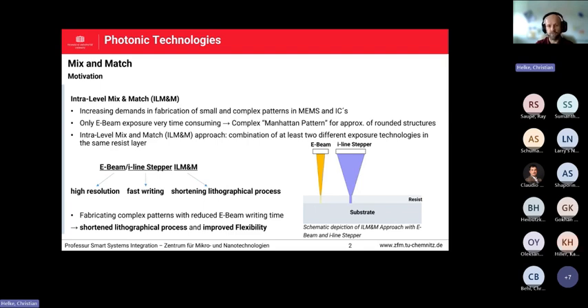Normally it's done in 2 different layers, meaning just do the lithography for the first layer, then etch the material below, do the second layer with some overlay compensation, and etch the second layer.